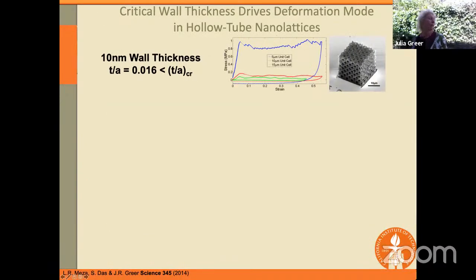So let's see what happens here. It turns out that for the 10 nanometer wall thickness, this critical ratio of T over A is below 0.03. And so what you can see is that for each unit cell size, for each type of sample, it fully recovers. And you can see that from the data, certainly going back all the way to the zero strain. And in this image after the deformation, you would never be able to tell that this is taken after the deformation because it looks exactly the same.